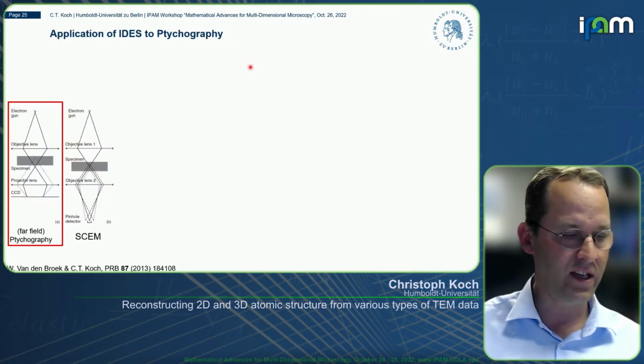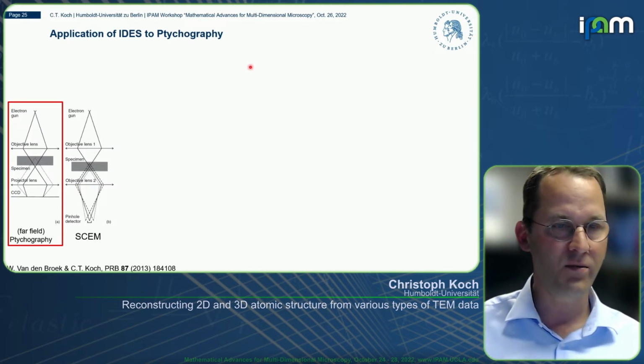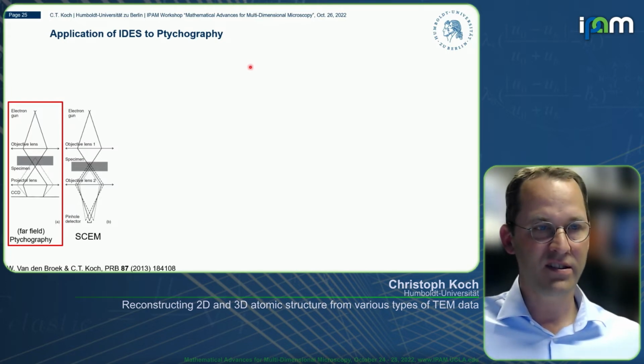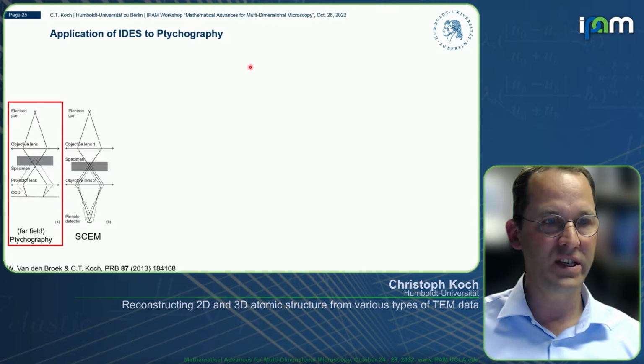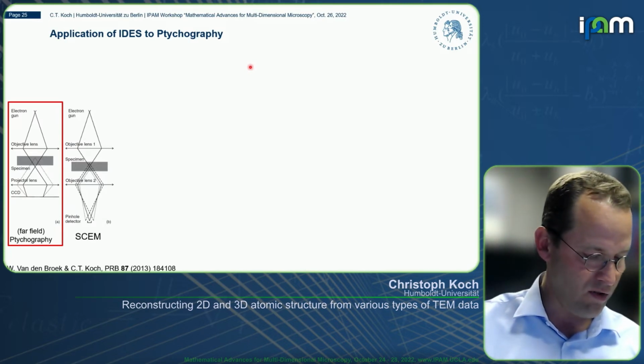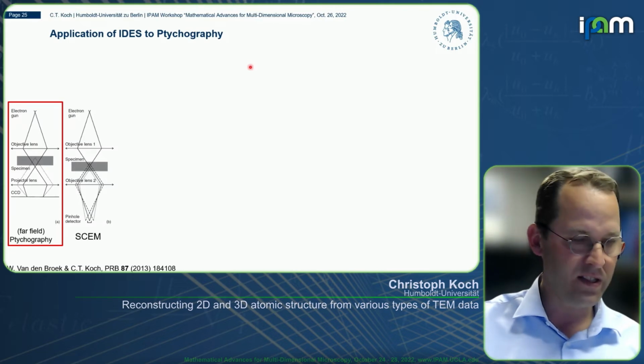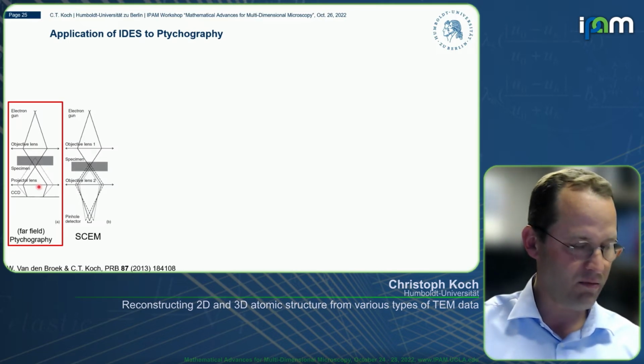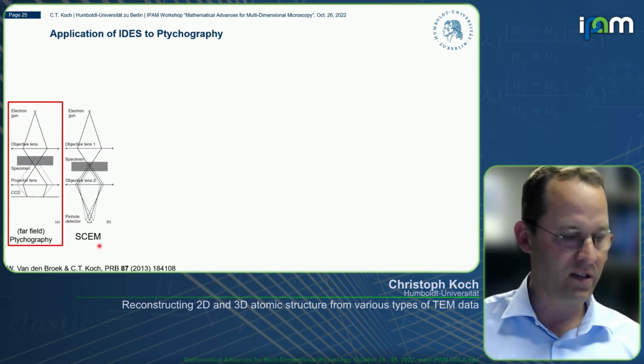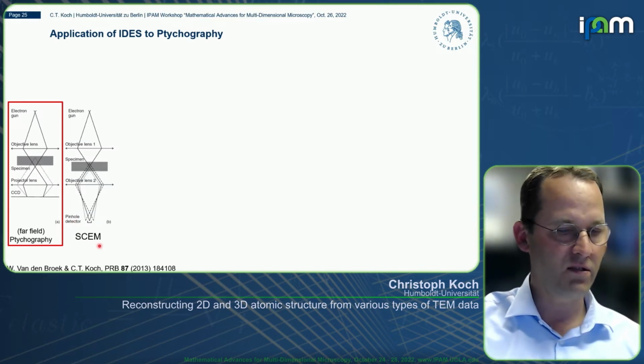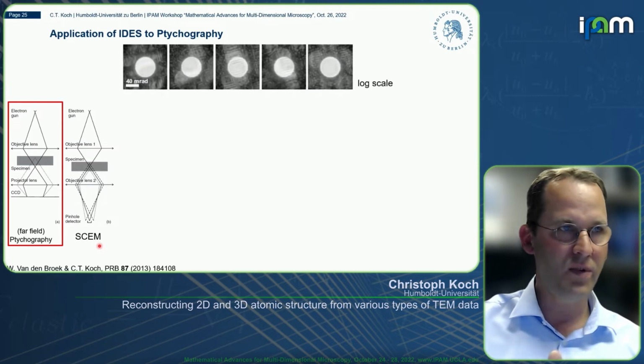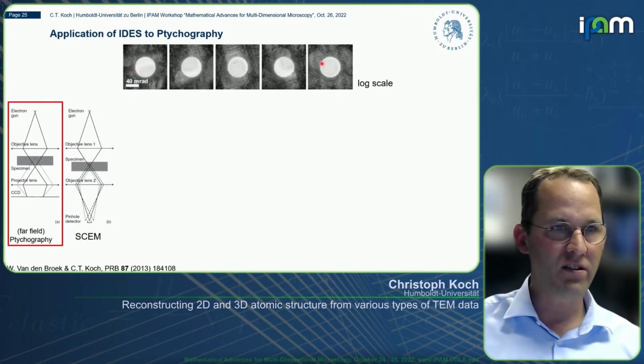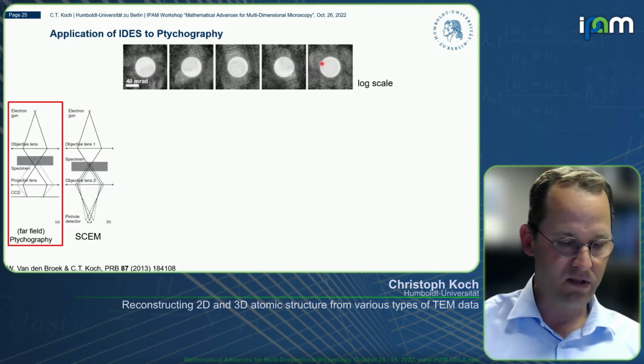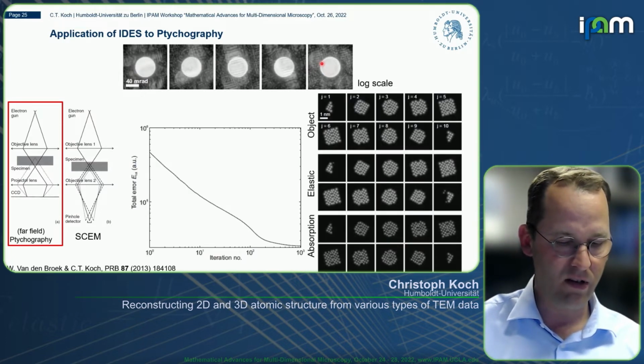And of course, HRTEM is, as I've already indicated, maybe not the best method for this. If we apply far-field ptychography, we acquire information to much higher scattering angles, and that, of course, also contains more 3D information. And so Wouter has then also, in a follow-up paper in 2013, investigated, for example, scanning confocal electron microscopy, but also this now very popular far-field ptychography. It was also popular back then, or it became popular, and he has simulated ptychography data, again while tilting the sample a bit and combining all this information at once. He was also able to recover the object potential.